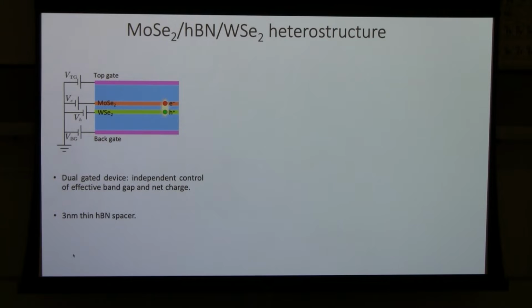So here is an illustration of how we make these electron-hole bilayers. We start with MoSe2 and WSe2, two semiconductor layers. We put a thin BN in between. Initially we use a relatively thick BN so that it allows us to create the electron-hole bilayer more easily, with more manageable applied electric field and bias voltage. So we have several different voltages applied to the individual layers. With 4 voltages, we can control 3 voltage differences, and that allows us to vary different parameters.